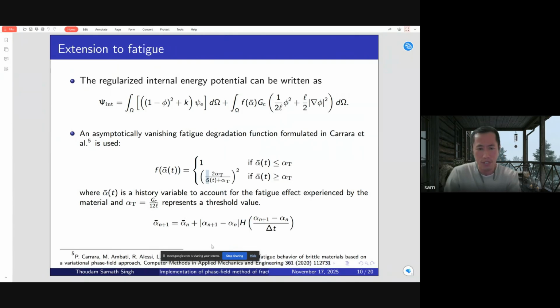This is the accumulated local energy of the material. As this grows bigger and bigger, this term will become smaller and smaller, and this term is associated with this GC. So as it gets smaller, the GC will also get smaller. This is how it degrades the GC when we have cyclic loading. And not only the cyclic loading, we can include hydrogen diffusion. We can also incorporate other effects, like the effect of heat. So all these things we can do.